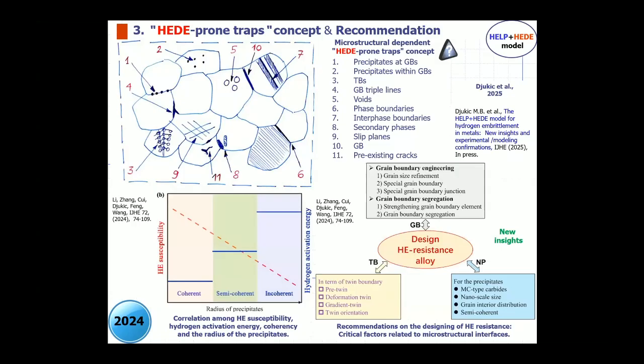This is the HEDE-prone traps. As you can see, localized spots in the microstructure: precipitates, twin boundaries, voids, phase boundaries, secondary phases, grain boundary, pre-existing cracks. Whether that location, when it's saturated with hydrogen, will provide brittle failure due to the HEDE mechanism application. So that's the investigation of HEDE-prone traps.